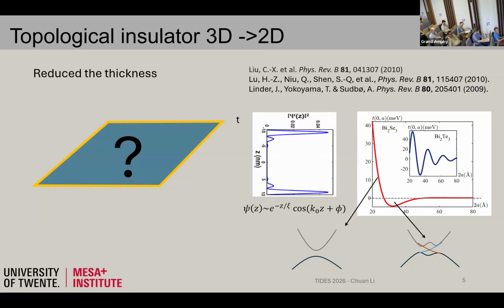And this is a very original work on the real number for the size of the gap and the thickness dependence. Of course, it depends on the material parameters. Because the material is layered, you cannot go in infinitely small steps. It always goes one quantum layer at a time, so these numbers are not continuous but discrete.